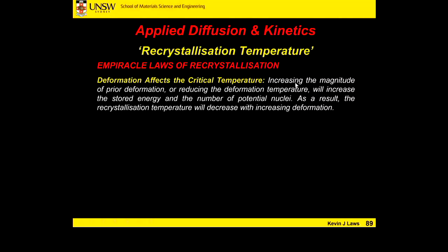So try not to make this too confusing. The temperature at which we work our material is also a little bit important: cold rolling versus warm rolling versus hot rolling. As we heat a material up while we're doing our deformation, that temperature allows the number of defects we're creating to be a little bit less. Material can flow more easily at elevated temperature, because atomic bonds can be dissociated more easily. It's easier for dislocations to glide at elevated temperature.